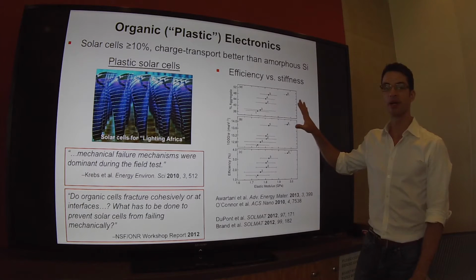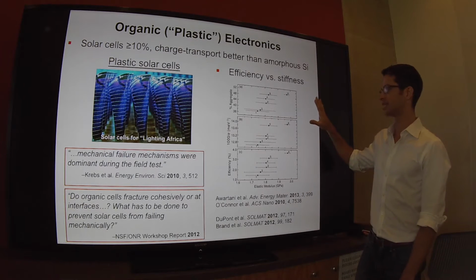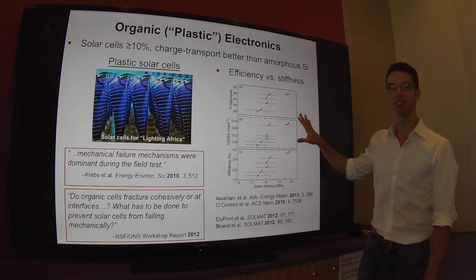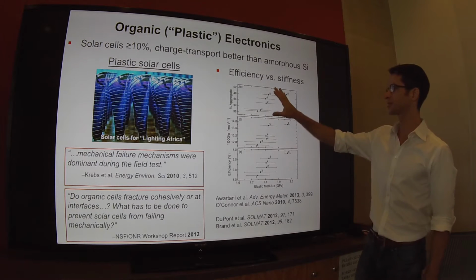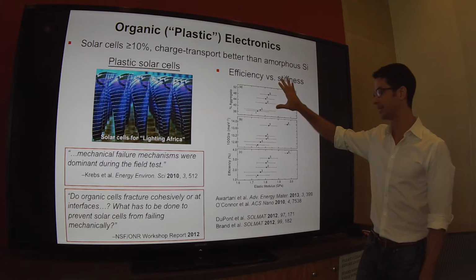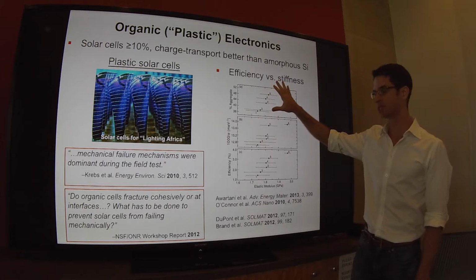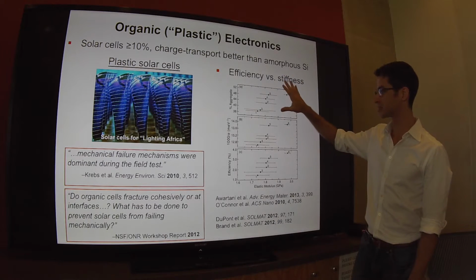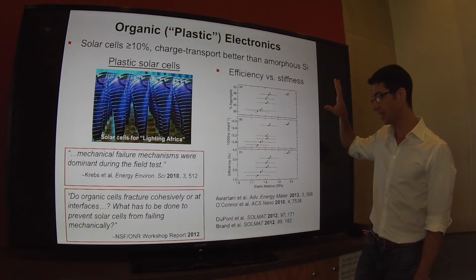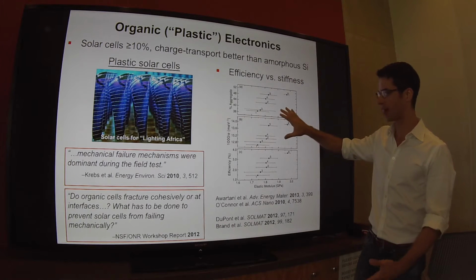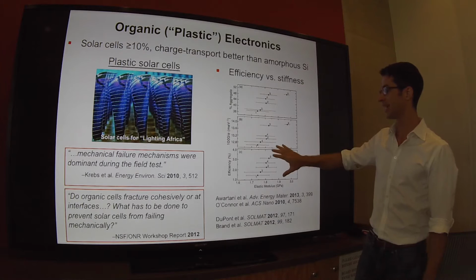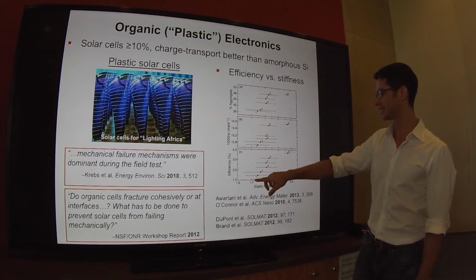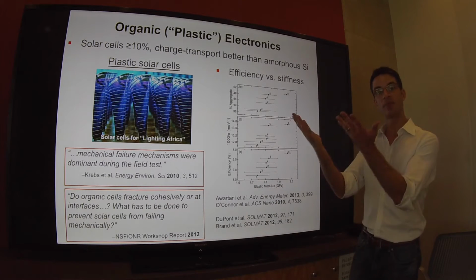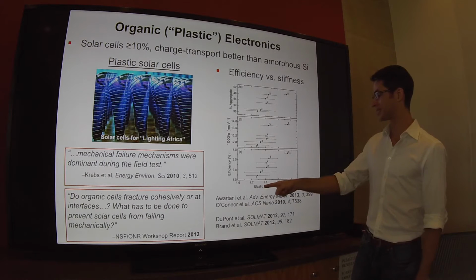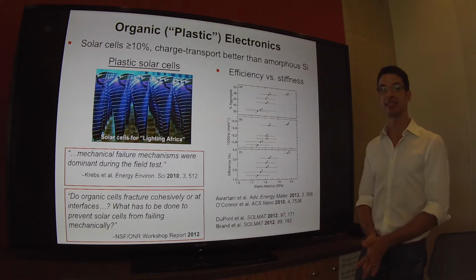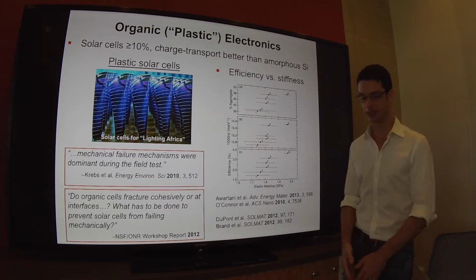In particular, Brendan O'Connor's group at North Carolina State University has published a very striking correlation between the spectroscopically determined order in an organic bulk heterojunction blend, so that's percent aggregate and the order parameter, don't worry about the details, and the efficiency. So what we find is that the order goes up, the efficiency goes up, but the stiffness, as manifested in the tensile modulus, also goes up.